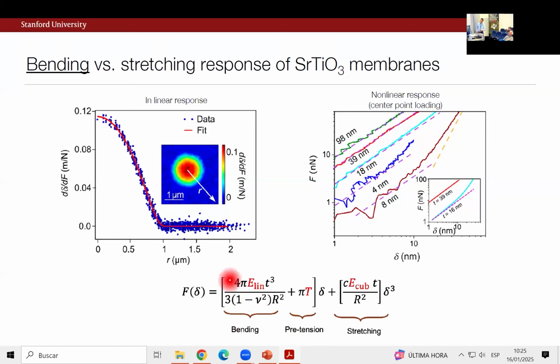And so the way you can get around this is then to do, in linear response, an extensive mapping of the force deflection curve. That is to say, you go around your drum head and poke in all different places in order to basically collect a 2D map of data from which you can extract and separately deduce the modulus and this pretension term.